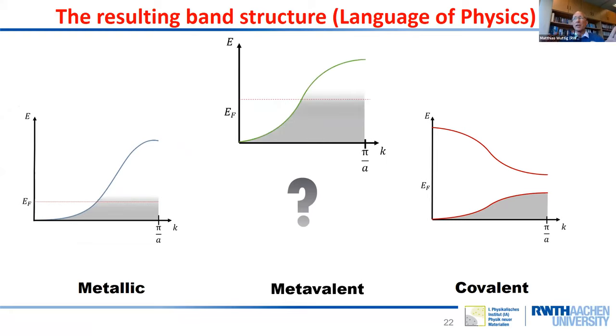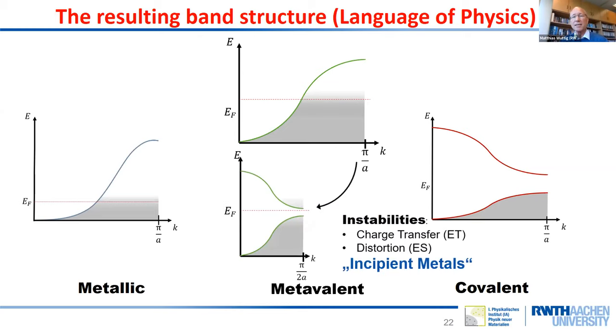And what we're encountering here is a situation where we have a metallic band, but this is half filled. Since, as we'll show you in a second, typically we form sigma bonds of p electrons, and there's just one p electron, but not two, to create a band. And this is a half-filled band. And interestingly, these half-filled bands are often unstable.